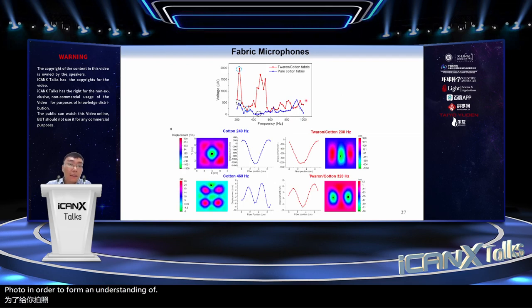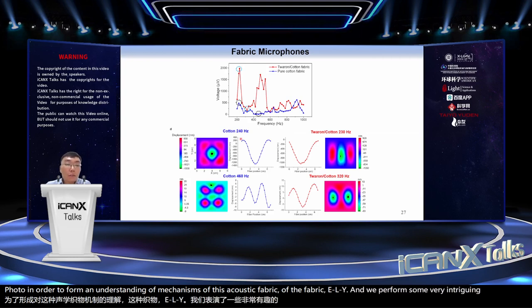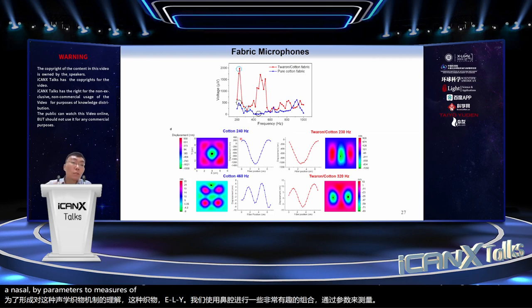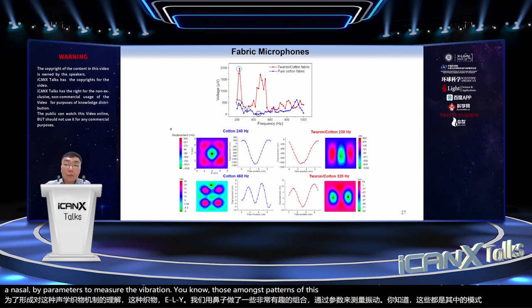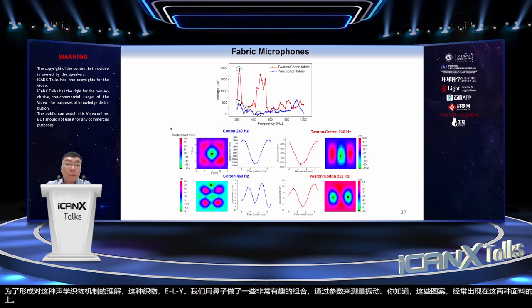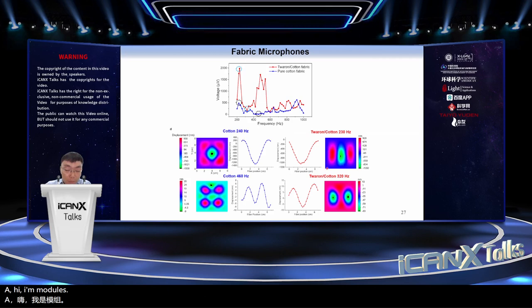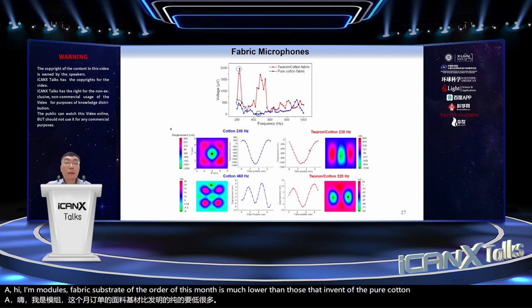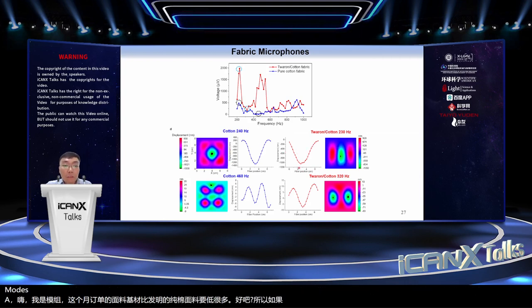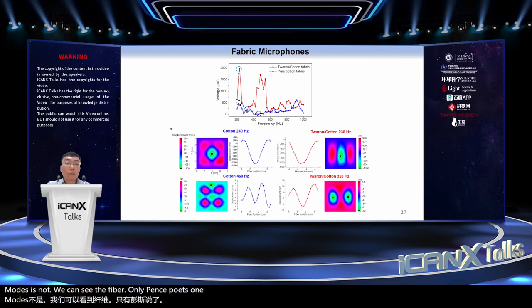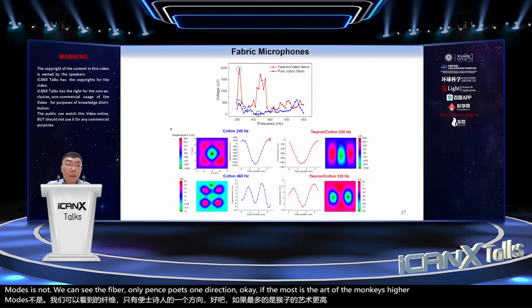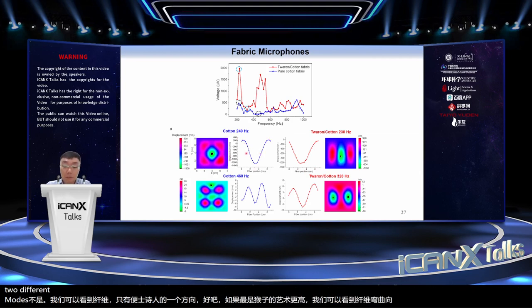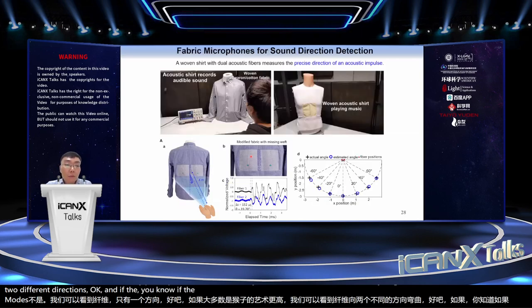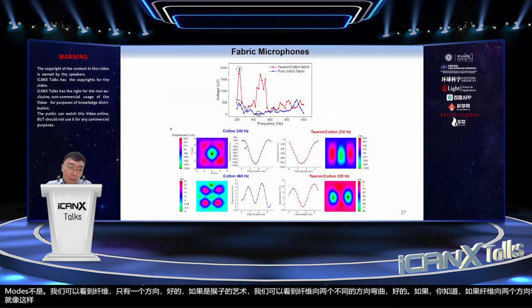And then, in order to understand the mechanisms of this acoustic fabric, or the fabric ear, we performed some very intriguing characterizations using laser vibrometers to measure the vibration mode patterns of these two fabrics. We can see that for the high modulus fabric substrate, the order of these modes is much lower than that of the pure cotton fabric. If the mode order is lower, the fiber only bends towards one direction. If the mode order is higher, the fiber bends towards two different directions.